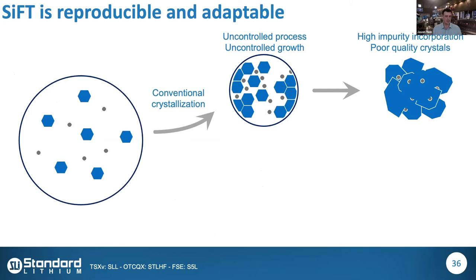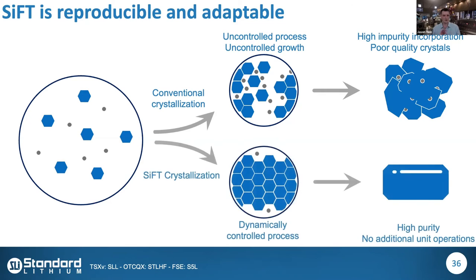In terms of crystallization, for people that have run this before, control is key. If you just take a lithium solution and try to do your crystallization, it's a relatively beast of a crystal, where what it loves to do is agglomerate. It forms together and tightly grabs whatever's in the solution phase. And this is what leads to a large amount of impurities. Coupled to that mass recovery problem, this is why batch crystallization becomes challenging for this material. You have to go through much more dynamically controlled processes in order to get this high purity material.